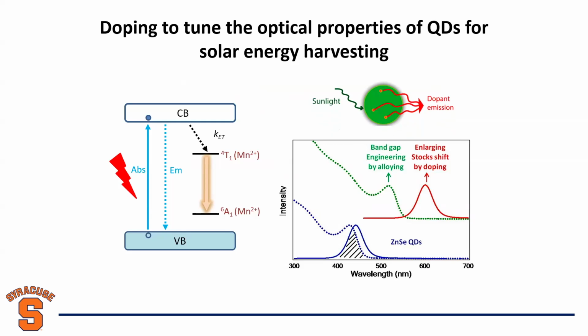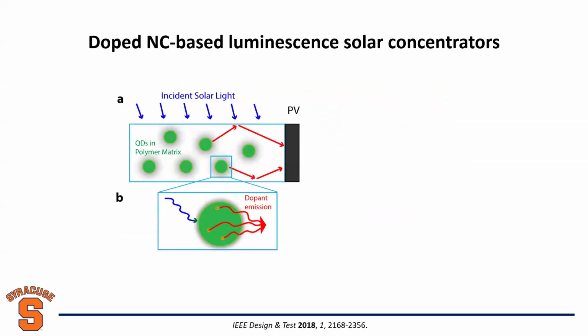Okay, and we use these particles to make solar concentrators. People have used solar concentrators for centuries, right? Initially, people used a big mirror to concentrate sunlight to cook or to boil water. But now we can use our functionalized, doped quantum dots. We put them in a transparent polymer matrix, and we can concentrate the sunlight. Sunlight is absorbed by the host lattice, with emission from the dopant.